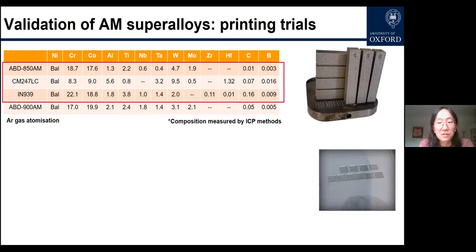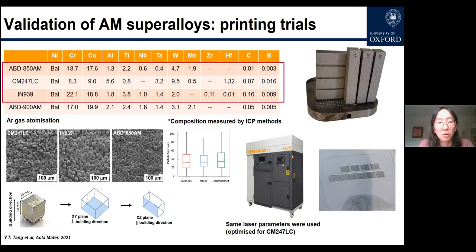These are the compositions of the material, and in short, we have made everything consistent. We just wanted to find out what the composition is really doing and how big this impact is. Try to convince ourselves, since we're not additive people. We made powder in the same size distribution. We tried the same laser parameters. We tried the same build volume and strategies, etc.